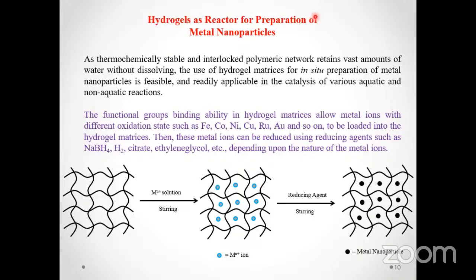These hydrogels can also be used as reactors for the synthesis of metal nanoparticles. So this is how the hydrogels are being used in nanotechnology. Once a hydrogel network is prepared, it's a very simple approach for the preparation of metal nanoparticles with controlled size, by controlling the mesh size, which can be controlled by controlling the cross-linking density and the concentration of monomers, which have different functional groups and which can absorb the precursor of the metal nanoparticles.